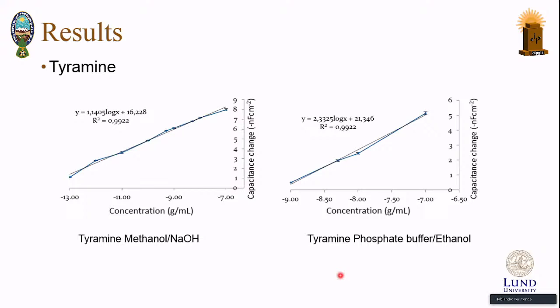When we were realizing the first paper, the best results came with tyramine. In the case of tyramine, we used two methods for electropolymerization. The first one was methanol with sodium hydroxide, and the second one, using phosphate buffer with ethanol. In the first method, we can see that we have a linear range of 10 to the minus 7 to 10 to the minus 13. And in the second method, 10 to the minus 7 to 10 to the minus 9. So we can see that when using methanol NaOH, we have a wider linear range and a lower value in here. This is, as we said before, by the self-limiting growth that this electropolymerization will have. So the gold nanoparticles over this tyramine will give us a large surface area.